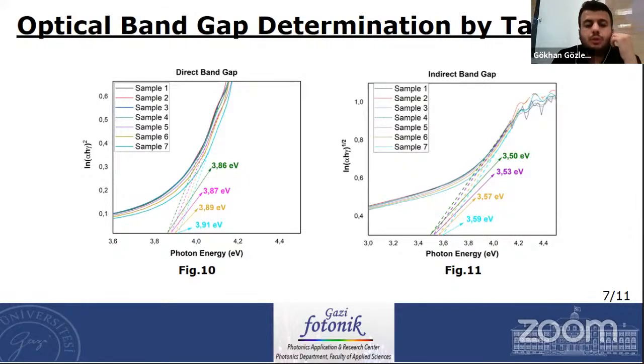The optical band gap can be determined by using the Tauc relation. In this relation, the direct band gap values have been calculated from alpha h-nu squared versus h-nu plots and are shown in figure 10. Corresponding band gaps were obtained by extrapolating the straight portion of the graph to the x-axis at y-axis 0. The value of direct optical band gap for sample 7 is 3.91 electron volts, sample 6 is 3.89 electron volts, sample 5 is 3.87 electron volts. Moreover, direct optical band gap of films thicker than 15 nanometers is 3.86 electron volts.